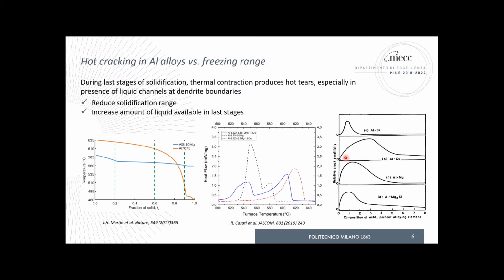The same was also true for copper, which is a dramatically dangerous element for cracking. Indeed, 2000 series alloys, 7000 series alloys, those that are critical, contain lots of copper. And again, you see here that we go through a critical range, but if we increase the amount of copper, then we can decrease the cracking sensitivity. Okay, we will talk about that later. If we move